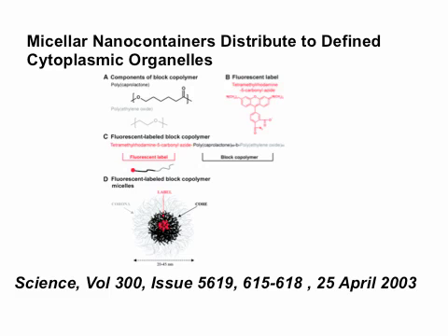So let's look at two of these things. I think it's a similar paper, but instead of a drug, let's just replace it with a fluorescent label. All I want to say here is that in this particular case, you have polyethylene oxide as the hydrophilic part and polycaprolactone, which is a polyester, so it's biodegradable at least, as the hydrophobic part. And then they covalently lock this group to the end group, which basically means it can't dissolve or Ostwald ripen out if it's crystalline. So that would work really well.